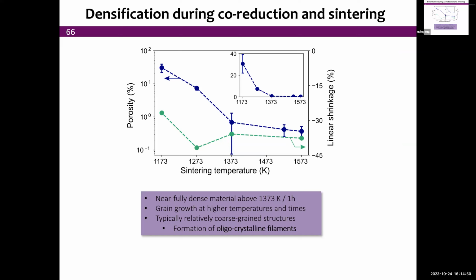All right, so in that particular case for this equiatomic alloy, we end up with nearly fully dense materials. This is porosity on log scale, so this is 0.1% here. We also get some grain growth at higher temperature, from submicron to tens of microns. Those are relatively coarse grain structures compared to the diameter of the filament. So we have what we call an oligocrystalline material, where the number of grains through the cross-section is typically less than 10, which is going to give us some variation in mechanical behavior, depending on which grains are oriented to which angle.